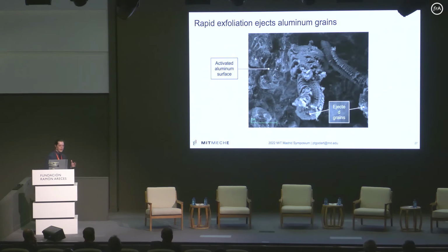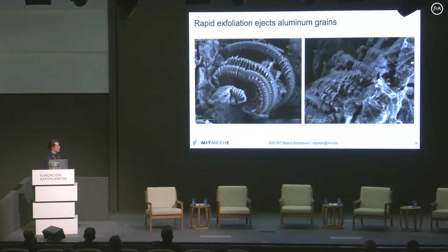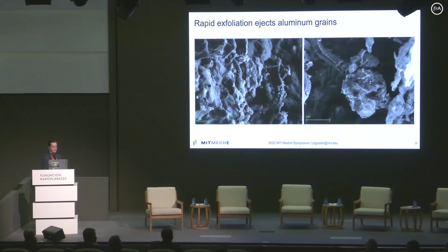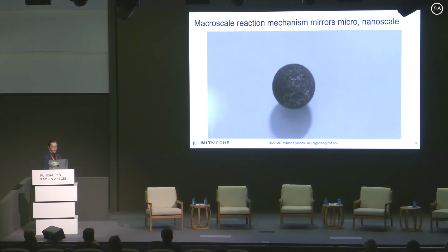Not only that, depending on the stress state of the aluminum that we input into this process, there are all these other secondary dynamic effects, like grain ejection, which had never been observed before, where you have this asymmetrical walking of the aluminum grains out of the surface in a very dynamic, very fast process. And this is also mirrored at the macro scale.